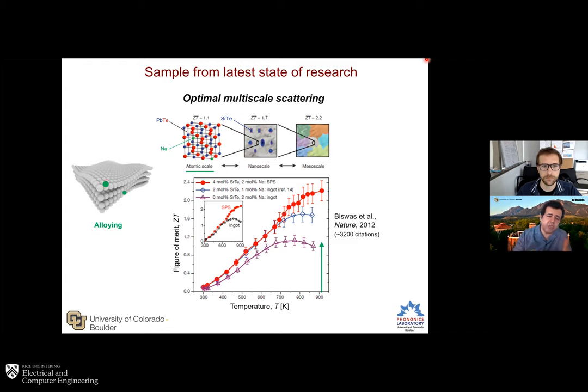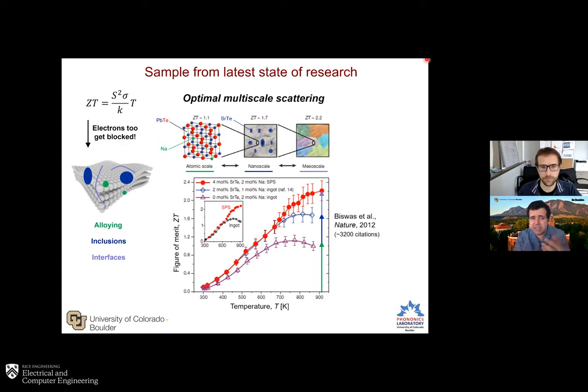If you look at this figure at the bottom, it's a figure of merit versus temperature. And you can see you can go quite high just by adding these impurities or alloying elements. Then you take another step and add inclusions at larger scale. And they've shown here through their experiments that you can go up further to perhaps a ZT on the order of 1.7. And then even further by introducing some polycrystalline microstructure with grains, they've shown that at high temperatures, you can reach ZT above 2, which is quite a high value. So again, to put it in the context of the ZT expression, these obstacles of different scales do a good job in reducing the thermal conductivity, but at the same time, they also block the electrons. So in a way, that's the key challenge.